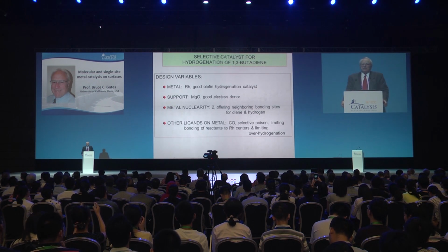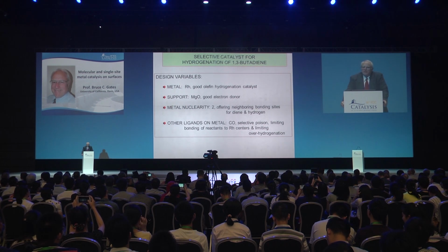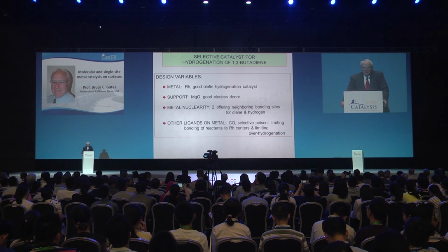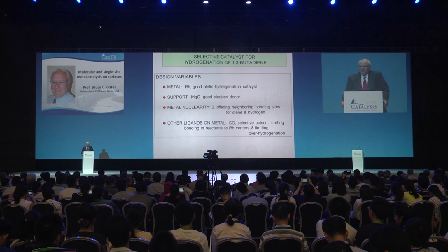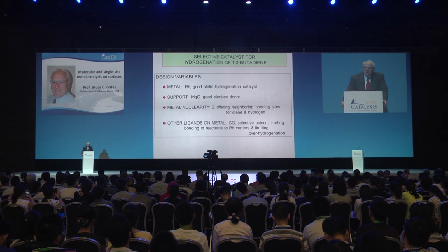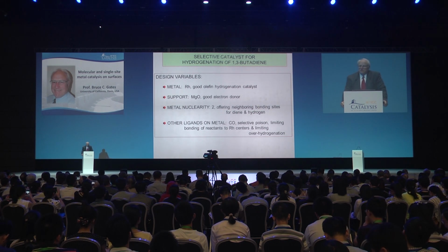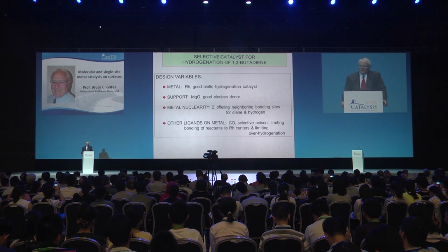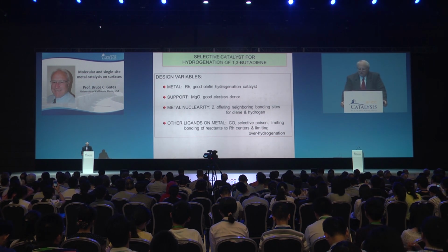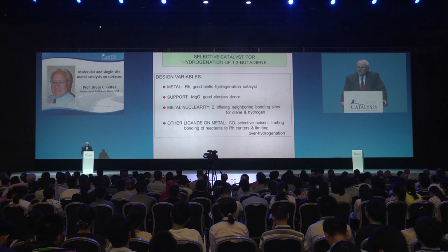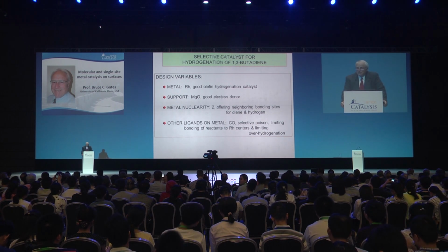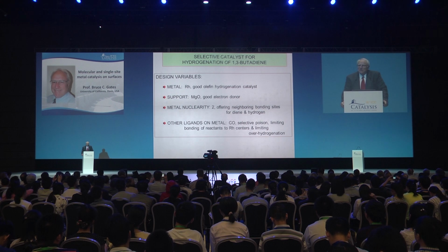I'm starting to get more daring with the use of the term design variables. The metal, iridium, doesn't work; rhodium does. The support needs to be a good electron donor—the zeolite doesn't work. The metal nuclearity is important: 2 works, 1 doesn't. And the other ligands on the metal are important, selective poisons if you want to call them that. The CO is necessary for selectivity in the catalysis.